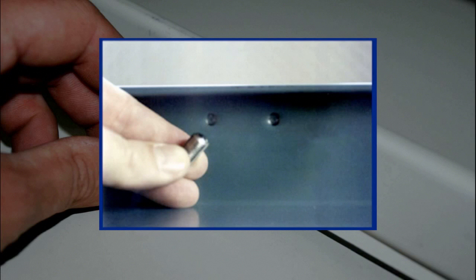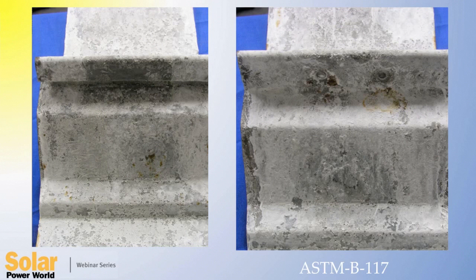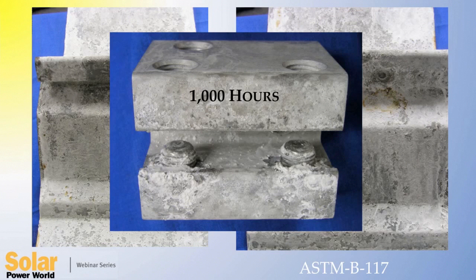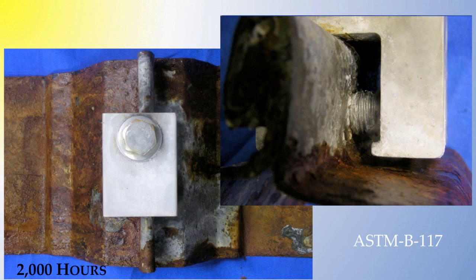S5 has also done extensive salt fog testing of the attachment to prove that it causes no premature corrosion to the roof. While 1,000-hour salt fog testing is considered the industry standard, S5 has doubled that, testing for 2,000 hours. And as you can see, even after the galvalume coating has completely corroded from the salt chamber, the clamp and set screws have induced no premature corrosion at their interface.